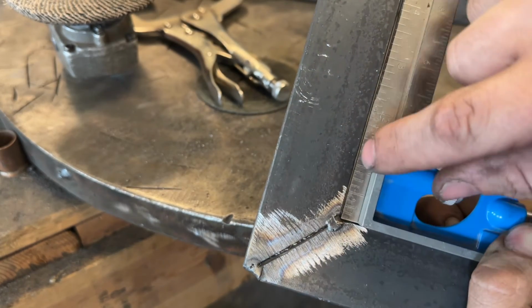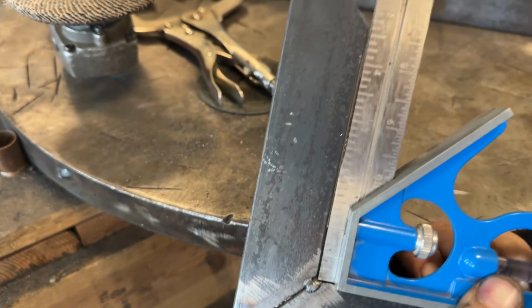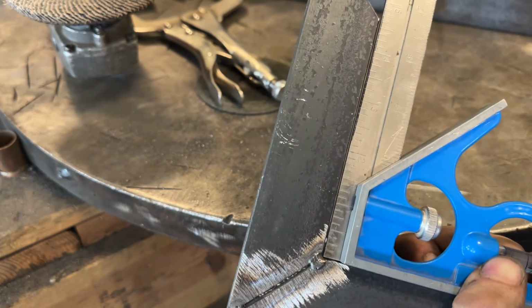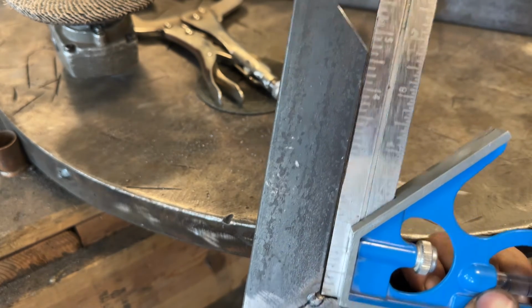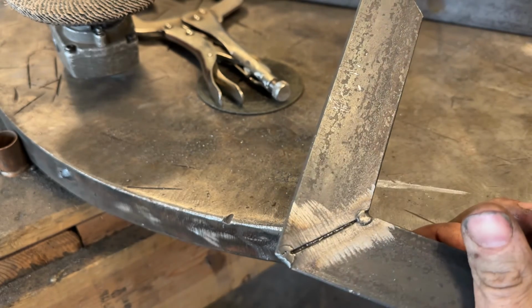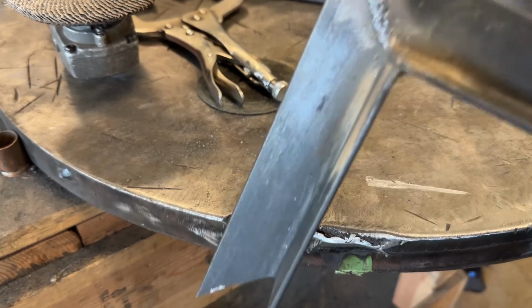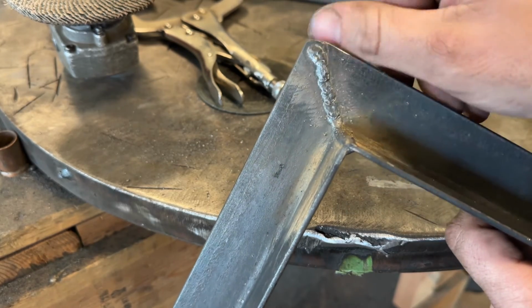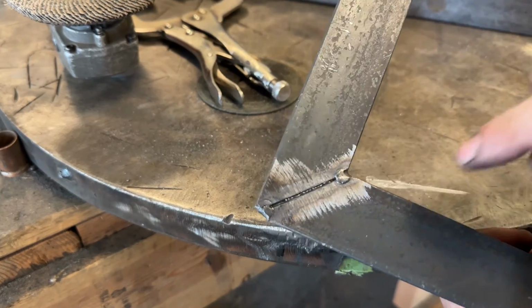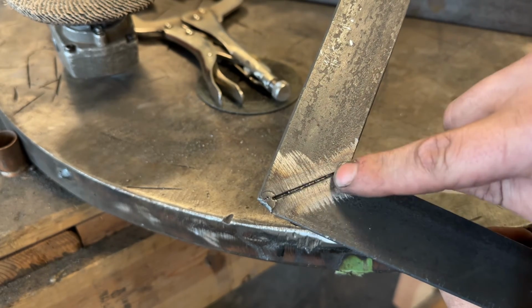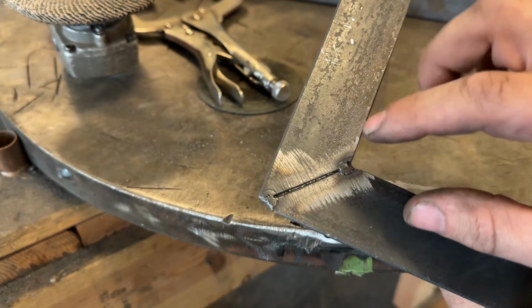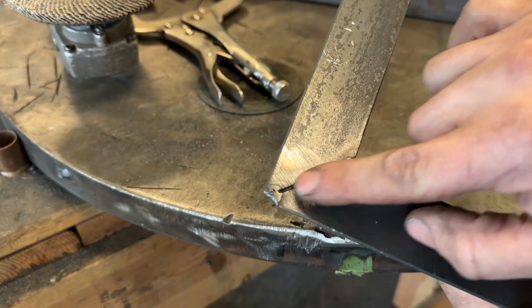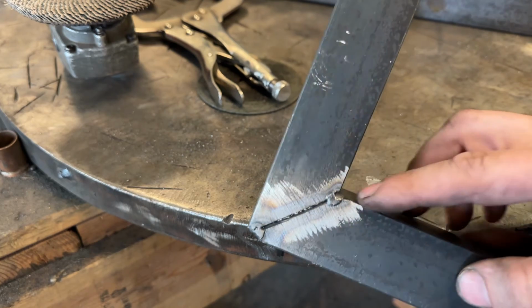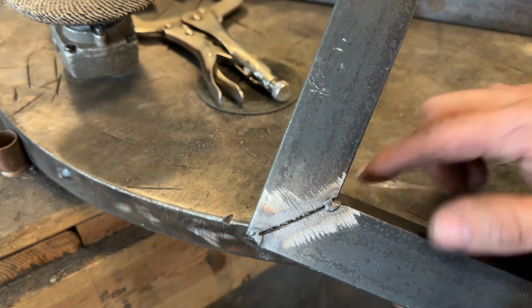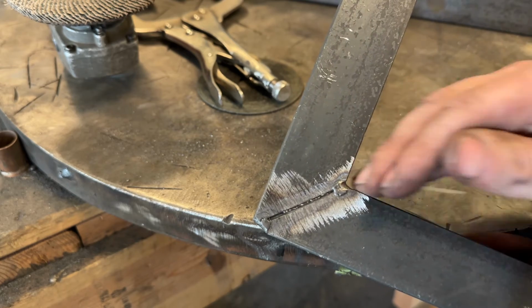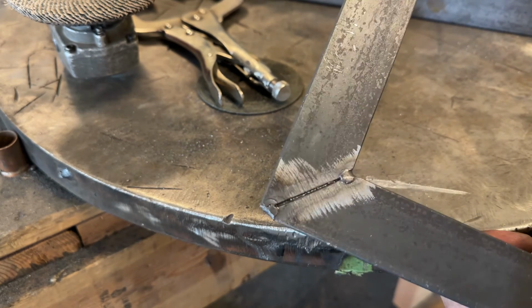So to show you, our gap is completely the same, bottom to top there. So we are officially square. Now, I welded this side with just a series of tacks, not the prettiest thing. I'm going to clamp it down and weld a series of tacks here. It's not going to shrink that much. And we'll finish that out, we'll grind this smooth, and then I'll take a grinder and clean this out a little bit to where we can have like a straight 90. Shouldn't be too difficult to do that.